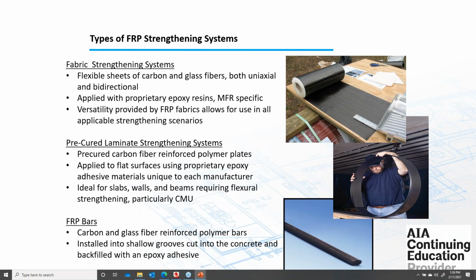But the actual fabric FRP products are used, well, they can be used for any strengthening scenario that you run into, but they're particularly beneficial for column wraps or shear U wraps around a beam. Anytime you have to turn a corner or make a 90-degree bend with the material, you're going to have to use the fabric, because the pre-cured laminates, the plates, while they come in a roll like you see there in the middle picture, they're not going to hold a 90-degree corner and stay bonded. That would be impossible. There's no way.